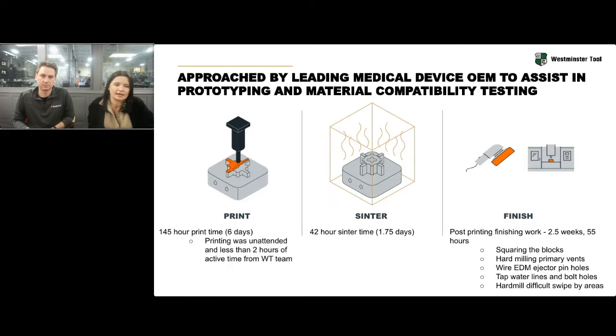The print took 6 days. That only is about 2 hours of attended time, prepping a build plate, moving it, starting up the printer, moving it over to the furnace, removing it from the furnace. I mean, it's 2 hours or less. It was just under 2 days of sintering. And then we had 2.5 weeks of post process that we did, which included tool making and assembly. And it was 55 hours of time to bring it to completion.